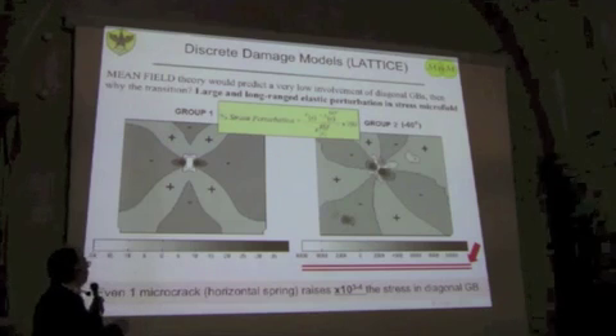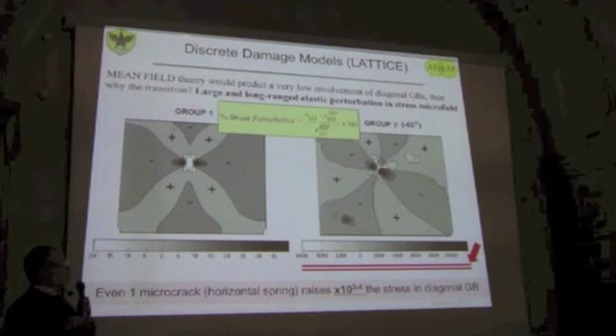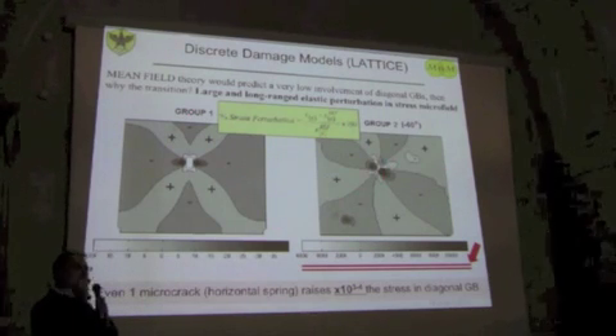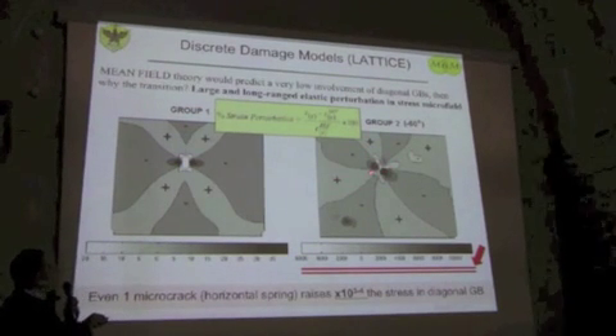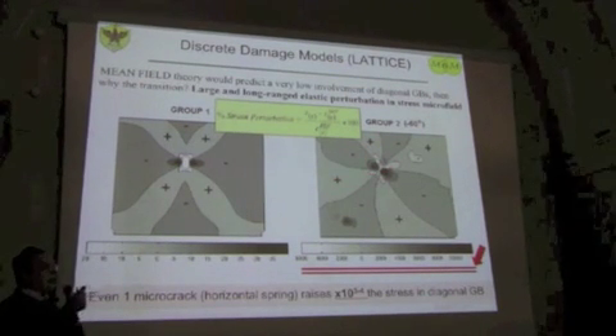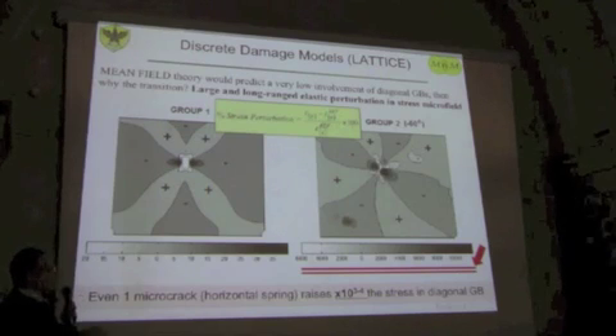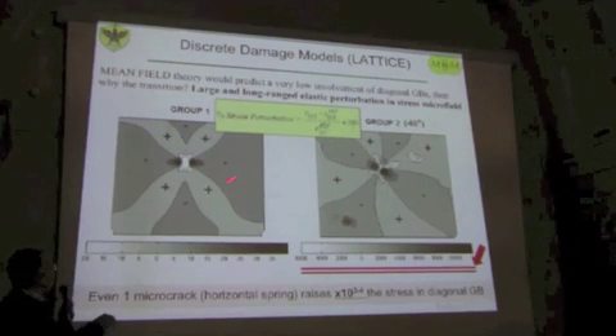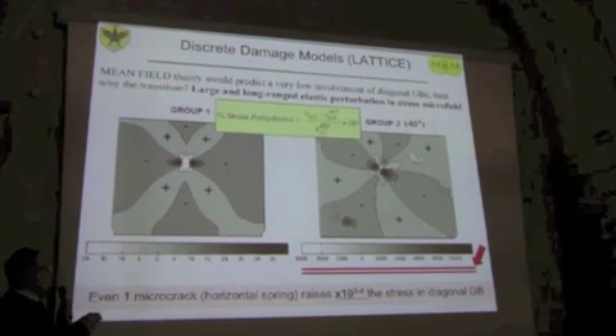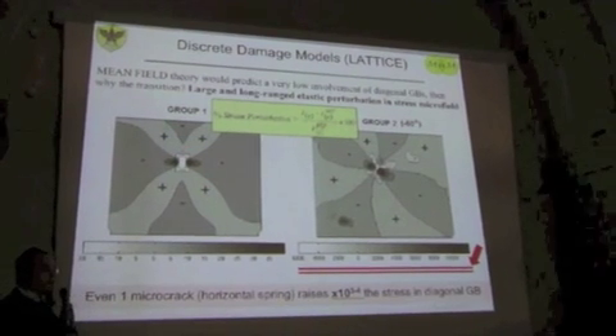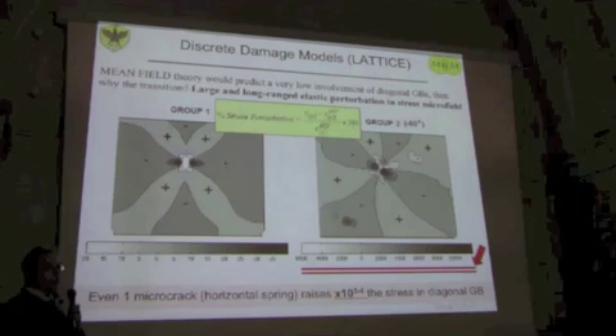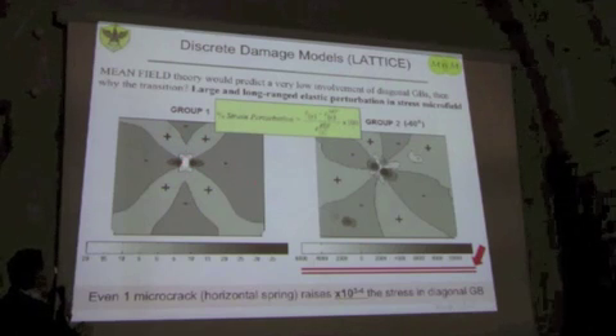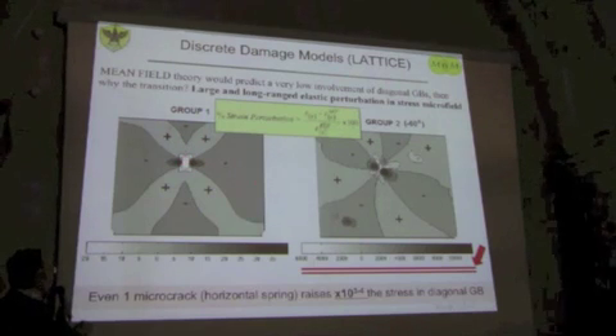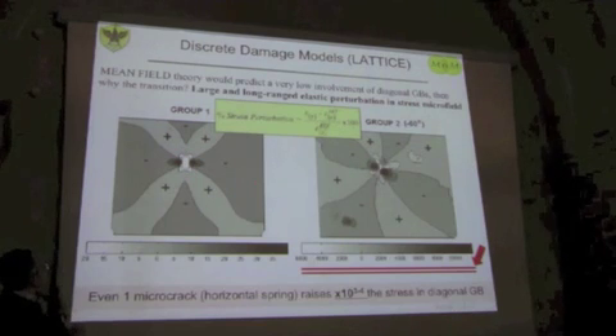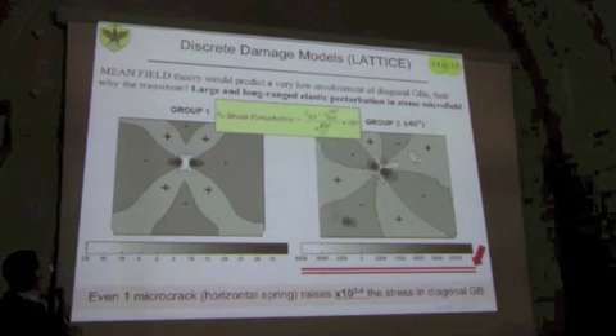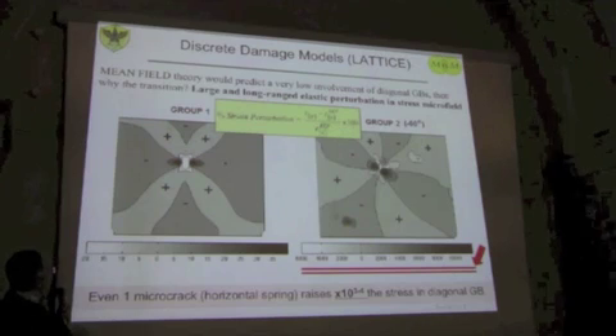Now, this is another interesting point. If we consider what is the nature of the building block of this process, it is really the fact that when I remove a link because a microcrack nucleates in the microstructure, since the very first one, like in this case, you immediately have a perturbation, an elastic perturbation field that irradiates over the domain. Now, this is the effect of a microcrack forming on horizontal links. Now the test direction is this one, okay?